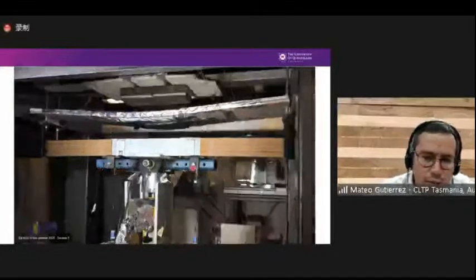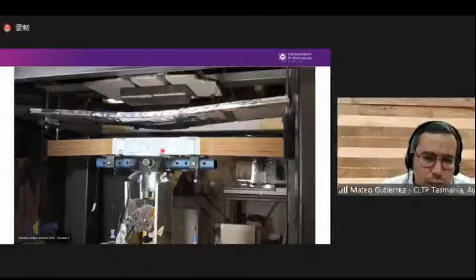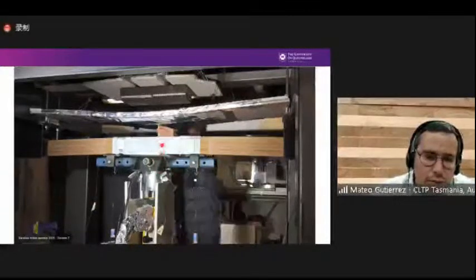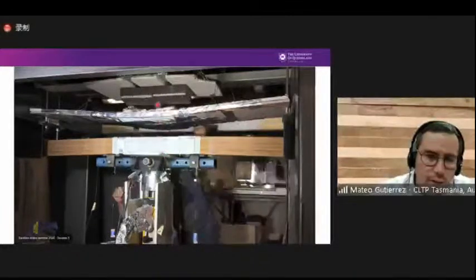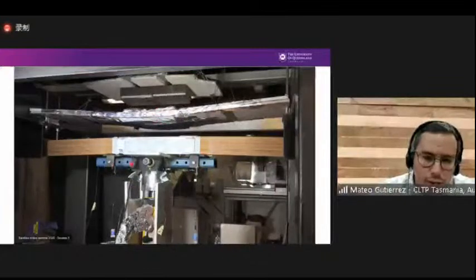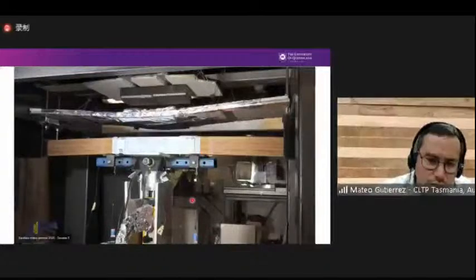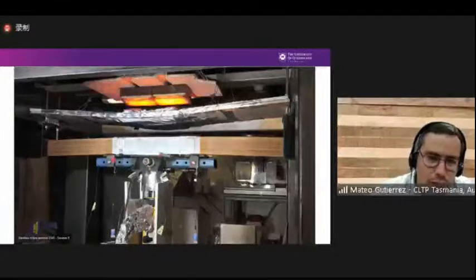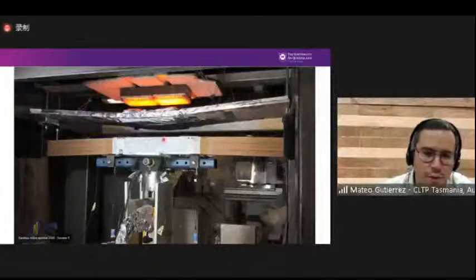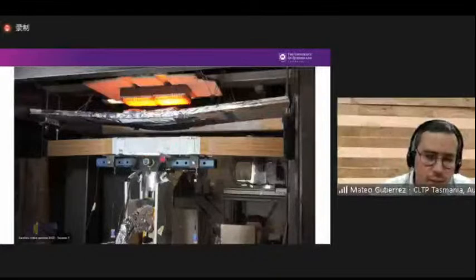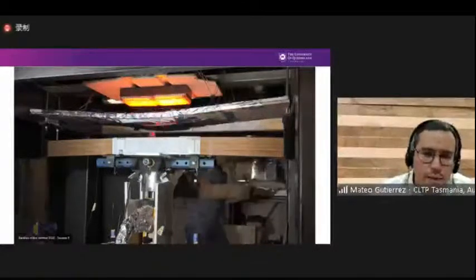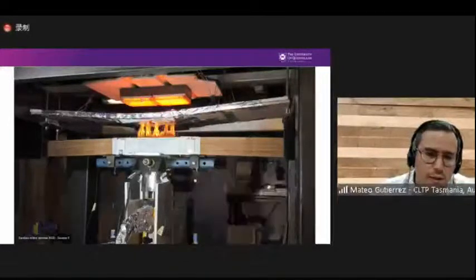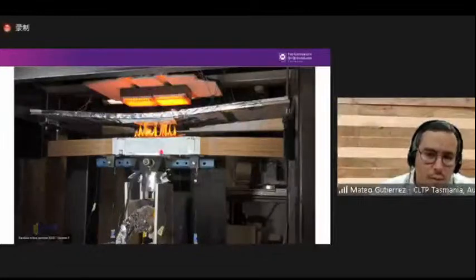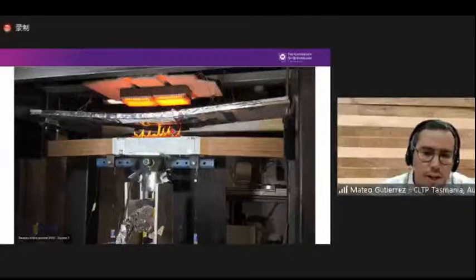So here you can see a video of one of those tests. Again, we start loading the beam until we reach the target load, let's say 8 kilonewtons. Then we define the distance between the beam and the radiant panels. As you can see here, we are measuring the flexions with string pots. We have strain gauges connected at the back of the sample, but we also have this area here that we marked with a speckled pattern that will allow us to measure the flexural strain with a DIC, which is a digital image correlation system. So basically, after these radiant panels apply an incident heat flux, we start burning the beam, and the beam starts having more and more deflections until it finally reaches the failure, right?